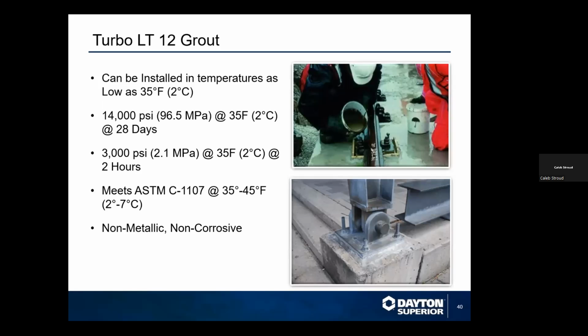And this is kind of a continuance on that with our turbo grout, but the main difference with this one is the LT means low temp. This can be applied below our 45 degrees, as we talked about earlier, and it can be placed down to 35 degrees. It can get up to 14,000 PSI at 28 days at the 35 degree marker. And it can also get 3,000 PSI within 2 hours at the 35 degree marker.